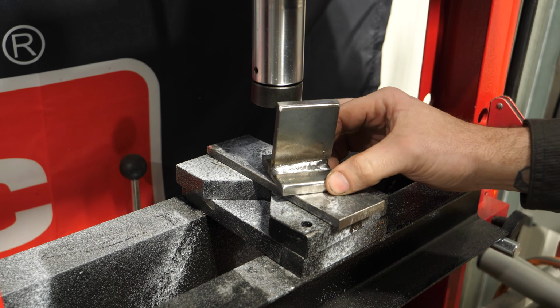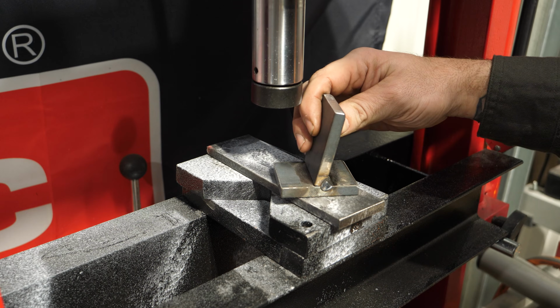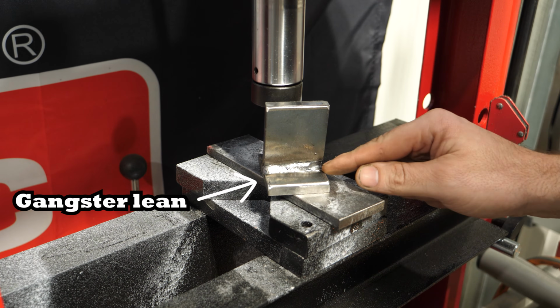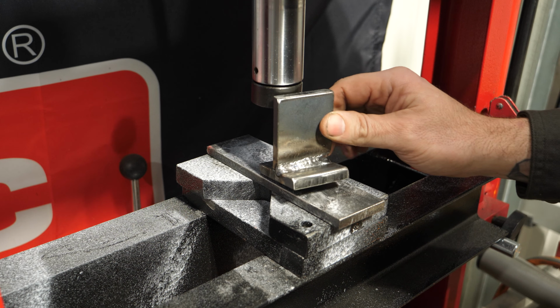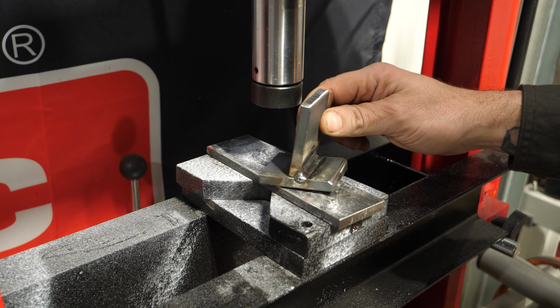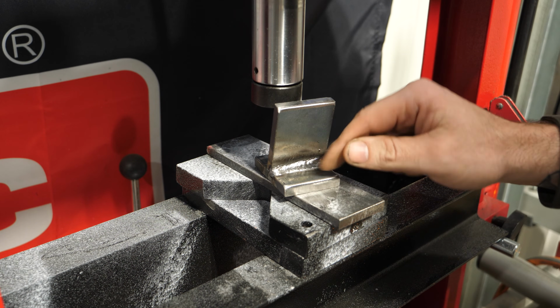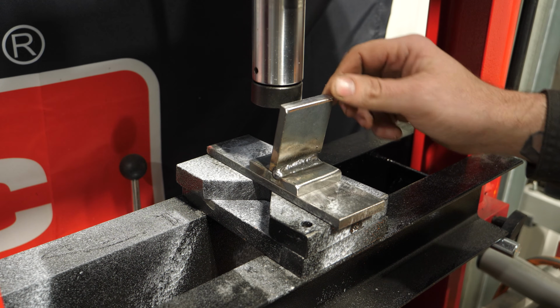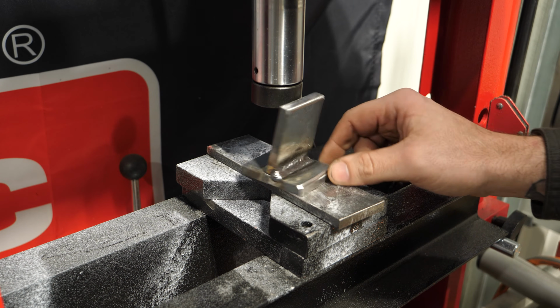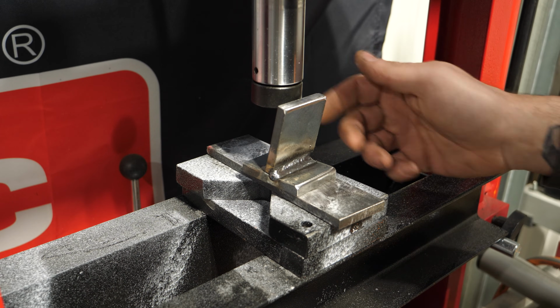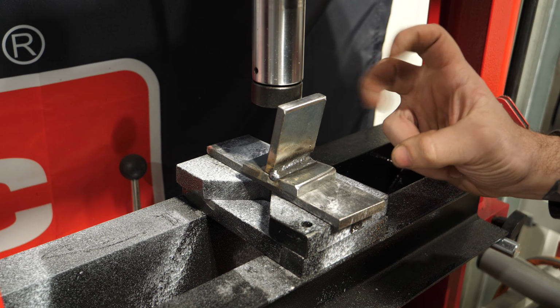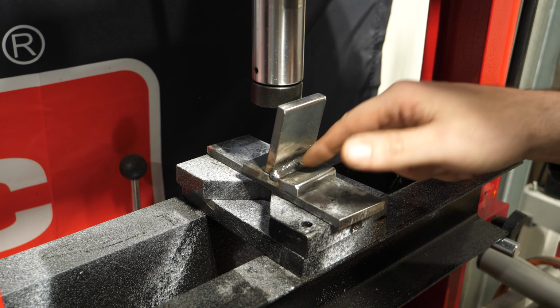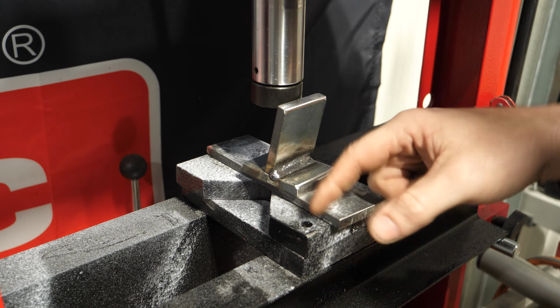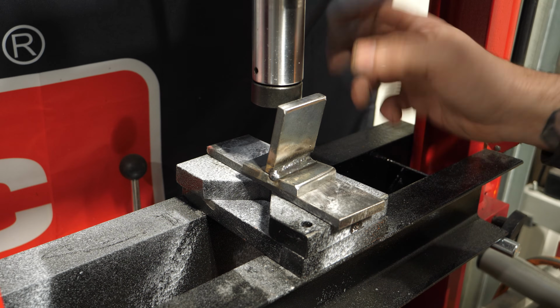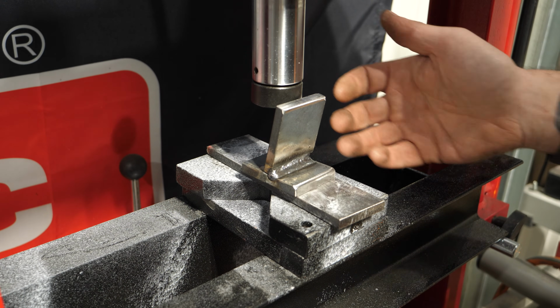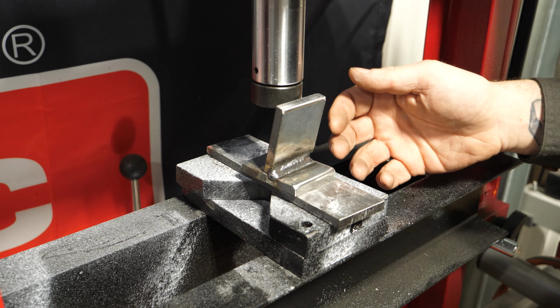So I got this guy set up. We're going to bend and break the one that's tilted a little bit. Weld-wise, it looks really good. It's flat. There's no undercut. It's at a proper 45-degree angle, so really nothing too much to write home about there. The end's a little bit blown out, as are most of these, and to really be fair, I should cut the section out of a middle part of a plate that doesn't have a start or a stop. That way it's more consistent, but this is a more realistic example of something you might weld.